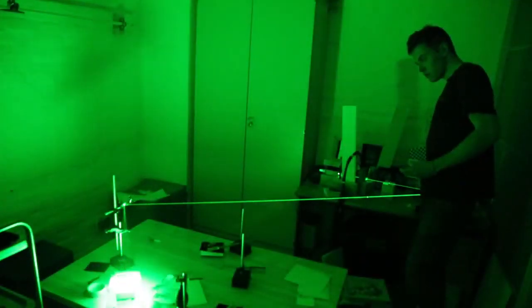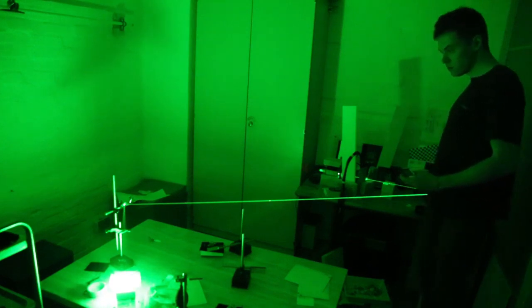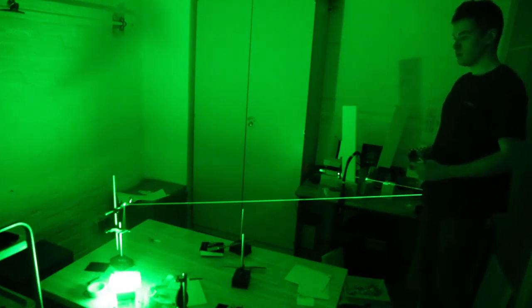By the way, in the first minute of the exposure, you can move the beam without a problem. As long as you don't move the table, it's all good and you can get away with a lot. In this setup, the exposure is done with a 100 milliwatt green diode laser at a wavelength of 532 nanometers. But I would much rather use a blue laser because DCG is 10 times more sensitive to blue light. The laser passes through a shutter and then through a rotatable polarization filter. This filter can be turned until the light is perfectly polarized.